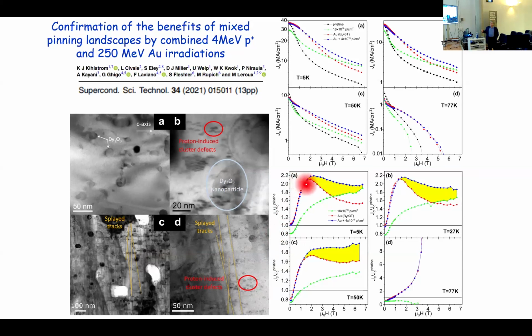By doing that, what we obtain is that the sample with columnar defects by heavy ion irradiation has a large JC increase at low fields. Then at about half of the matching field, it started to decrease, and that is true at all temperatures. The proton irradiation produced some deterioration at self field and low fields, and then an improvement with field. And the sample with both is better than any one of them. So you take advantage of both, this mixed pinning landscape acts in cooperation to produce stronger pinning.